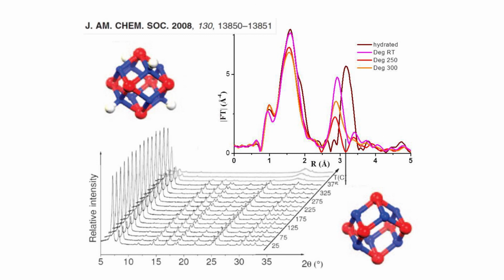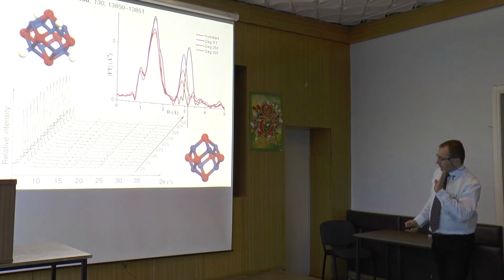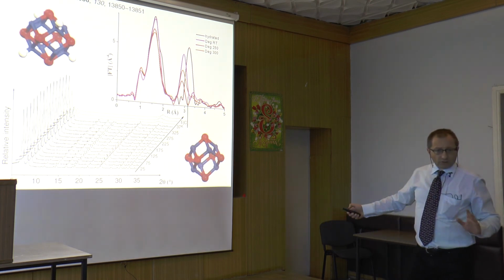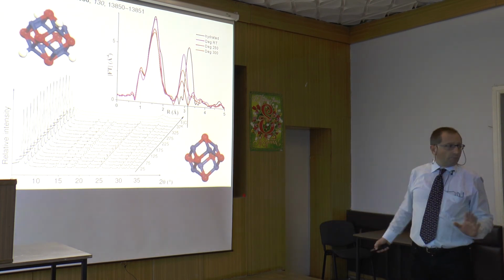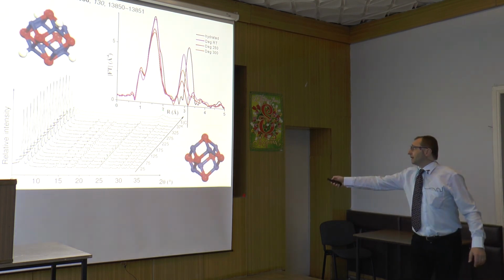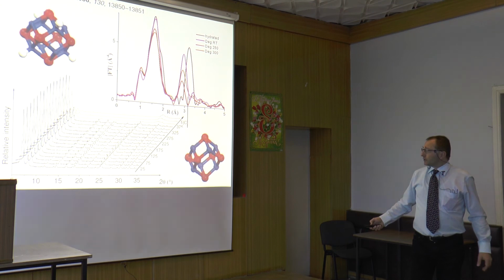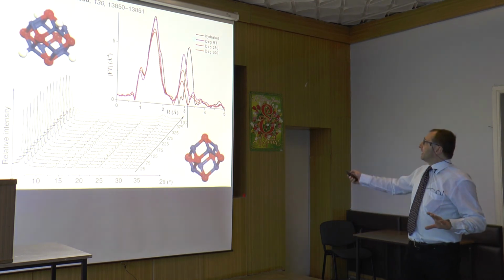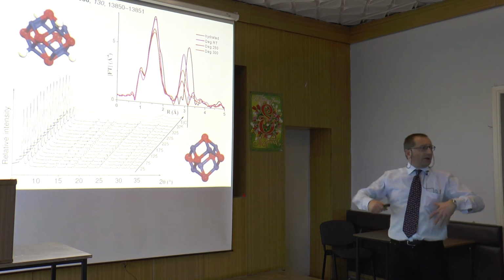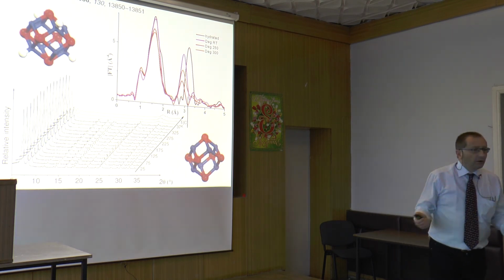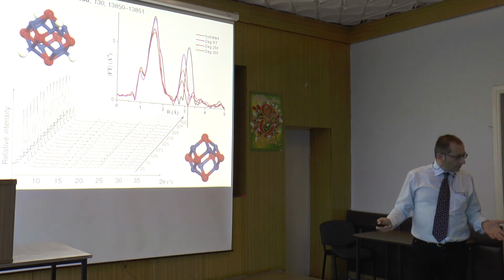So the interesting thing is that we have a huge change in the zirconium distances upon removing the solvent. And these changes were not observed by X-ray powder diffraction, because this is the temperature-resolved X-ray powder diffraction experiment, where we always see the same peaks. Only at the end the system changes, but there we are destroying the MOF. So we have to understand why EXAFS sees a very huge contraction of this. So we have a very huge change in the local geometry that is not observed by X-ray powder diffraction.